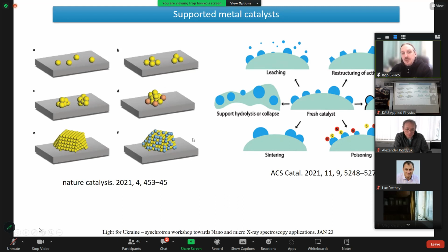And of course, if we talk about catalysts, it is a solid material, but it is not an ultimately stable solid. Reaction conditions, chemical reactions, influence this solid. And this leads, for example, to the sintering of catalysts. So we can create, for example, catalysts with very small nanoparticles, but during reaction, these particles sinter with creation of large nanoparticles. It can also be poisoned by some components of the reaction mixture. It can, for example, be covered by carbon and therefore deactivated.